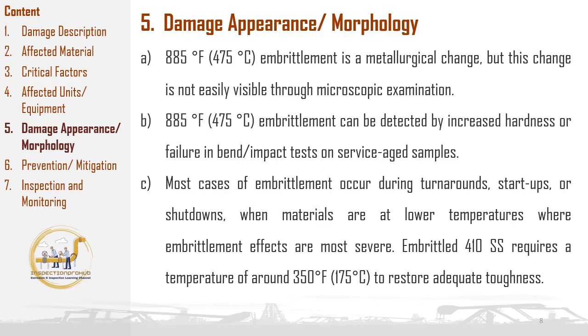Embrittlement commonly occurs during turnarounds, startups, or shutdowns, when materials, such as 410 stainless steel, are exposed to lower temperatures where embrittlement effects are most pronounced. To restore adequate toughness in embrittled 410 stainless steel, it requires heating to around 350 degrees Fahrenheit, allowing for the recovery of its mechanical properties and reducing the risk of failure during service. Proper temperature control during these critical phases is essential to prevent embrittlement and maintain material integrity.